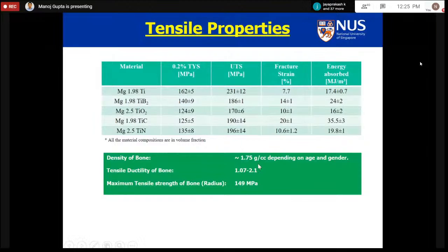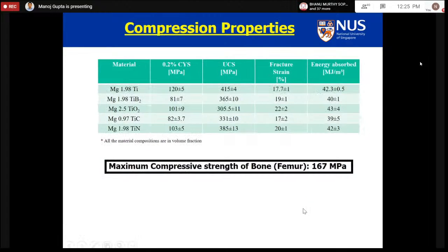So we worked on some nanocomposites containing titanium, titanium diboride, titanium oxide, titanium carbide, and titanium nitride. We want to see whether their mechanical properties are good or not, whether they can sustain that bone fracture or not. So we found that the strength of the bone is about 149 megapascal, and our maximum strength is much more than that. The ductility is only between 1.07 to 2.1. The ductility is good, so our material is stronger and tougher, and the density of bone is the same as that of magnesium. So it merges very well with the bone.